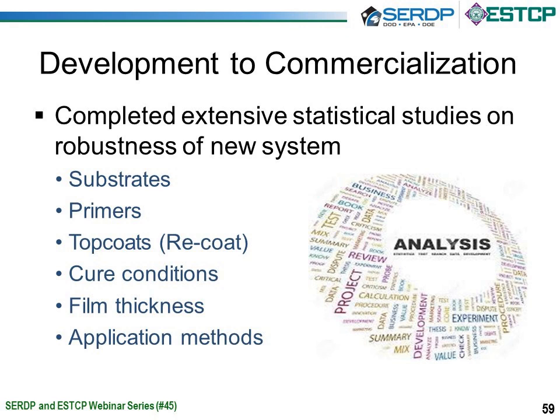The cure conditions, and when I say cure I mean application conditions and methods, we want to understand how we can apply this coating at 100 degrees in Mississippi, for example, in the middle of August, or in Iceland in December, and understand what the limits of the coating are, as well as the film thickness. We all know in an ideal world, the military specification has a specific film thickness identified. We want to understand and recognize that those ideal conditions aren't always followed. So if we go above film, below film, what's the maximum and what happens once we get outside of that range.